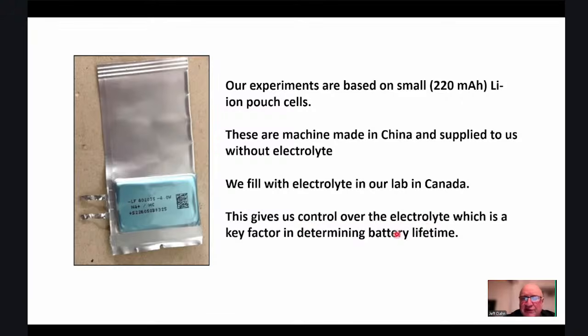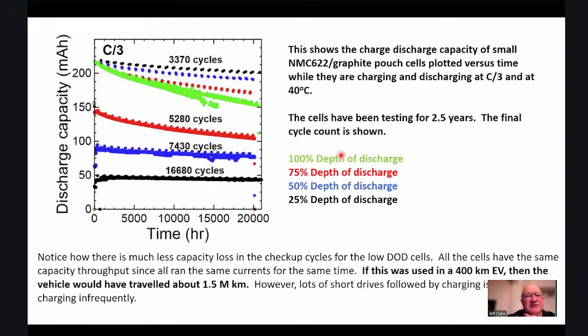And having control over the electrolyte is a key factor in determining battery lifetime. So here's some data that comes from a paper published a few years ago that shows the discharge capacity versus time in hours. So this graph represents almost 3 years of testing. For NMC 622 graphite pouch cells, they're operating continuously at 40 degrees C and charging and discharging with a current that would cause the cell to do 100% state of charge variation in 3 hours. So that's called the 3-hour charge and a 3-hour discharge.